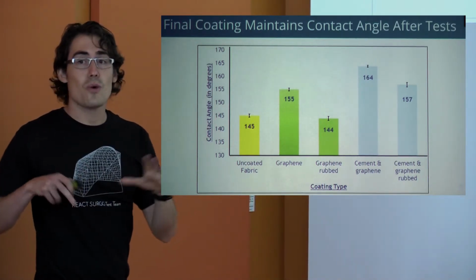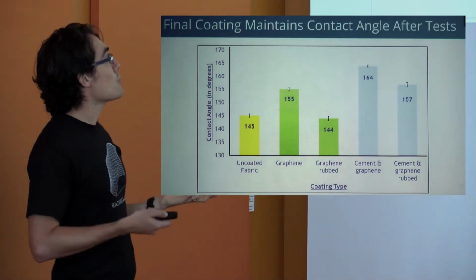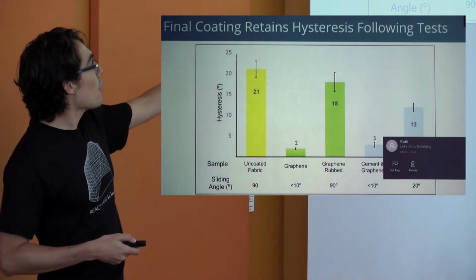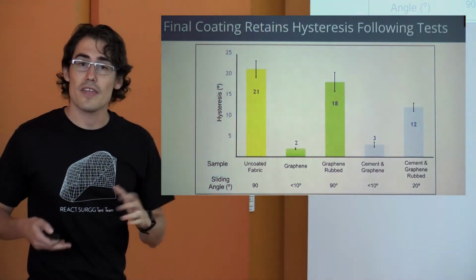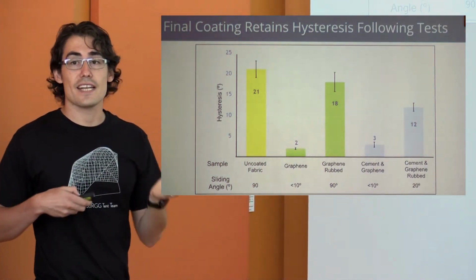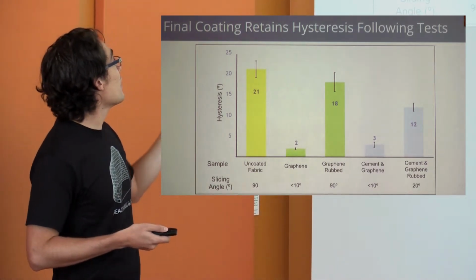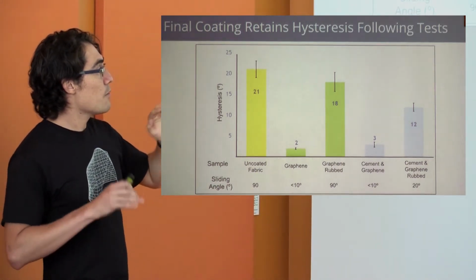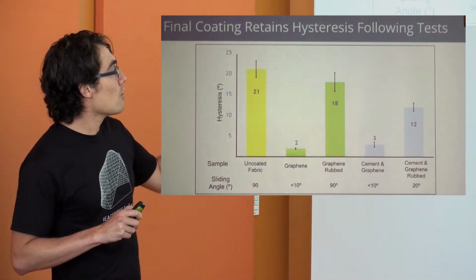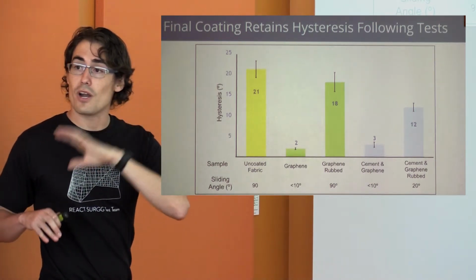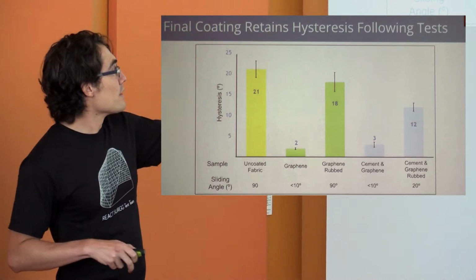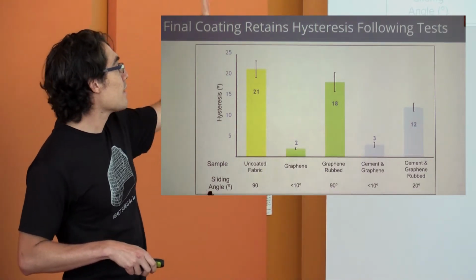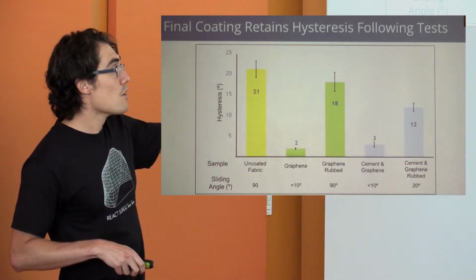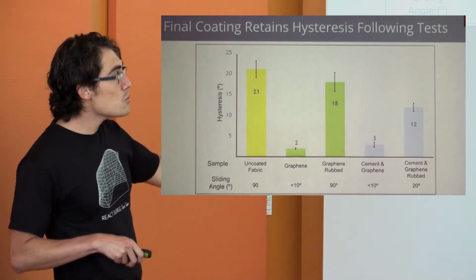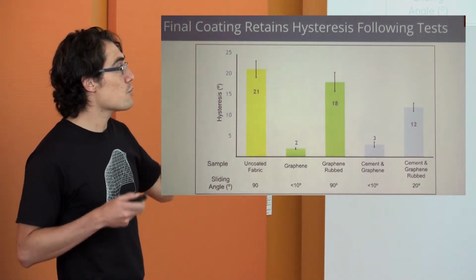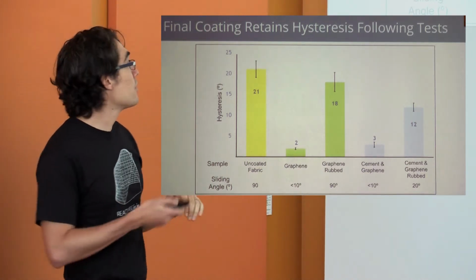Again, as Griffin mentioned, we don't want it to be only super hydrophobic, we want it to be slippery. So we did the same type of comparison. We can see that the uncoated fabric gives us an angle hysteresis of 21, and this translates to a sliding angle of 90 degrees, or more than 90 degrees, which is not what we want. Now, the graphene and the cement with graphene, in their pristine conditions, give us a sliding angle of under 10 degrees. So this is almost flat, and the water will just bounce off. But without the cement, the graphene rub comes back to a very high sliding angle and a very high hysteresis, while the cement with the graphene rub does lose some of this low hysteresis, but it maintains enough to still be a significantly low sliding angle.